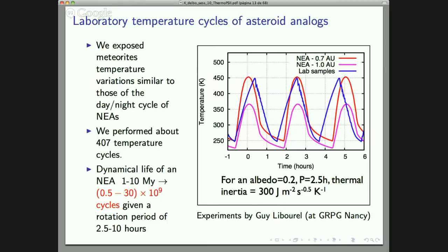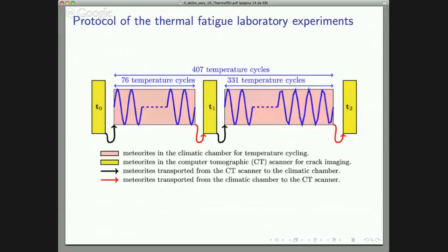And this is our laboratory experiment protocol. Here is a sketch of what we did. Before we started the cycling, we did X-ray tomography of our samples to look inside. Then we did a week of cycles. Then we took them out of the chamber for another scan, and then we put them back for almost a month during the summer vacation in France. Nobody touched the chamber because nobody works. When we returned from vacation, we took them out and scanned them again with the tomographic scanner.